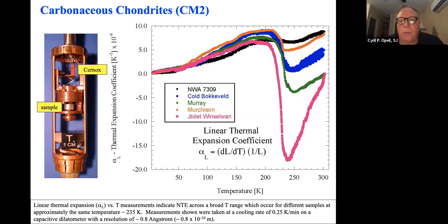And then I asked him, what is it? And he said, I haven't a clue because I'm not into meteorites. But he said, that's a second order transition, as opposed to a first order transition. And now you have to find out what that is. But really what's important here is that eventually these materials go through this huge transition, they bottom out, and then they come at 300 Kelvin back to almost zero. They're a bit distorted, but it's important. And I'll tell you in a minute why this is happening.